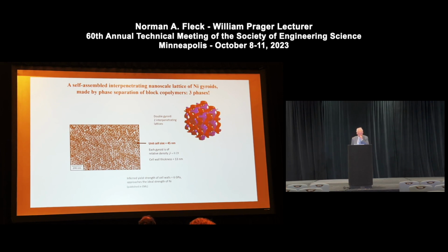The topology of the gyroid in that configuration is a so-called bending structure. It's pretty weak in terms of its configuration. So the overall macroscopic strength of this double gyroid is not as impressive as you might expect it to be, but that's because of the knockdown factor associated with the waviness of the gyroid, analogous to what I mentioned in the dermis, where wavy collagen fibers reduce the modulus.